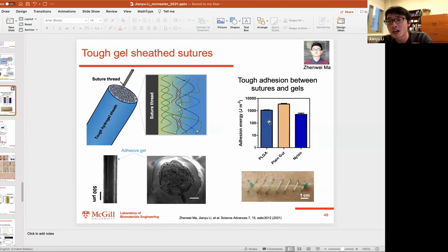Yes. So in terms of the detailed fabrication, I just introduced the chemistry. In terms of fabrication, it can be reacted in a defined capillary tube to define the thickness we want to achieve. We can really tune the thickness, or we can pull in the suture using a dipping method. But in that case, we have less controllability of the thickness. It's not as confined as the capillary tube approach. Yeah. Okay, thank you. That makes sense.